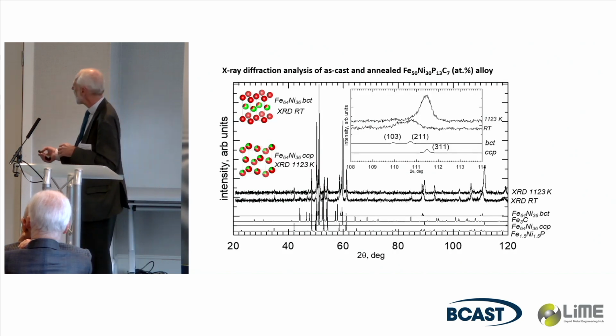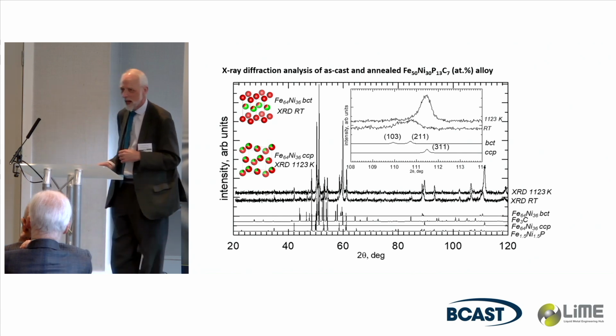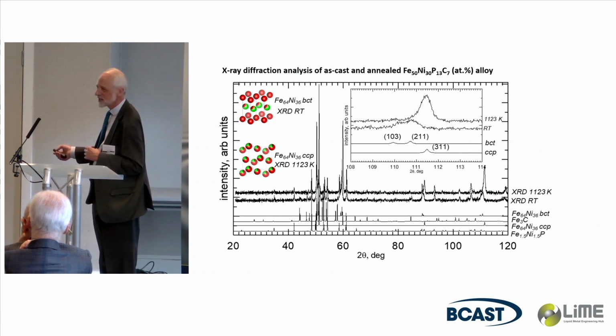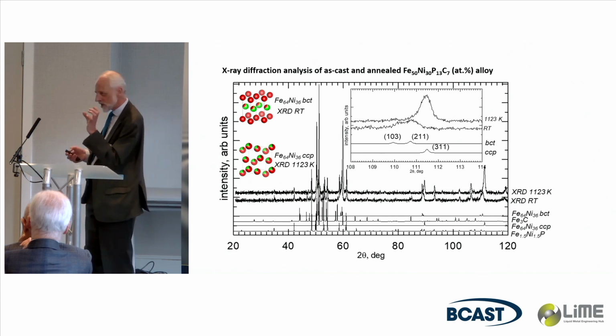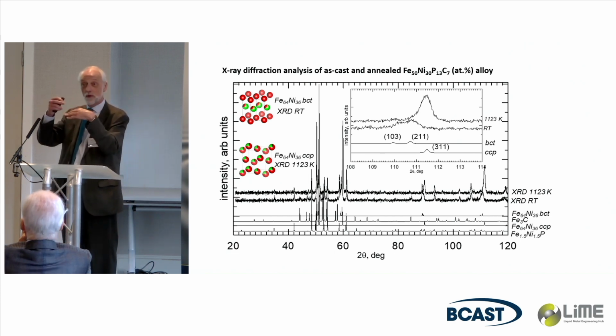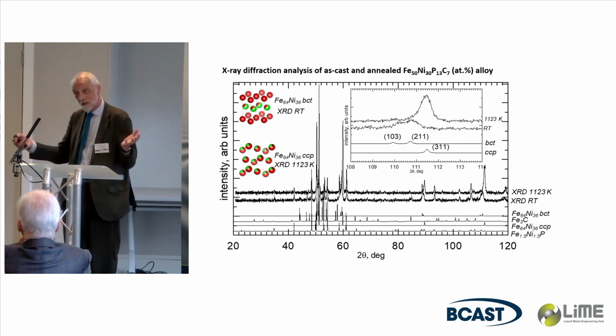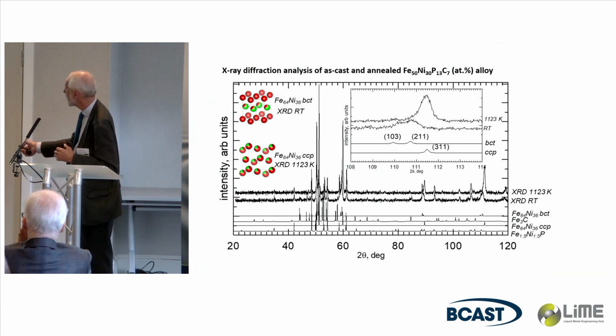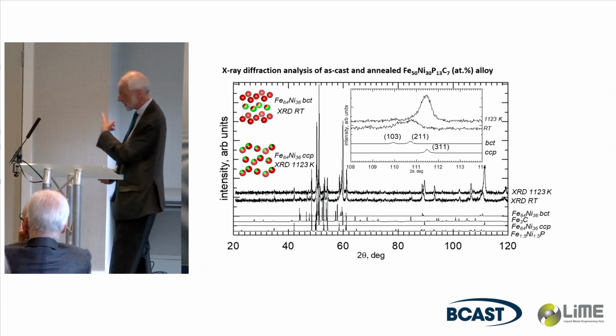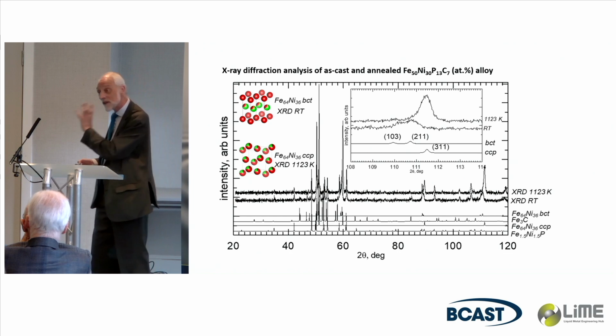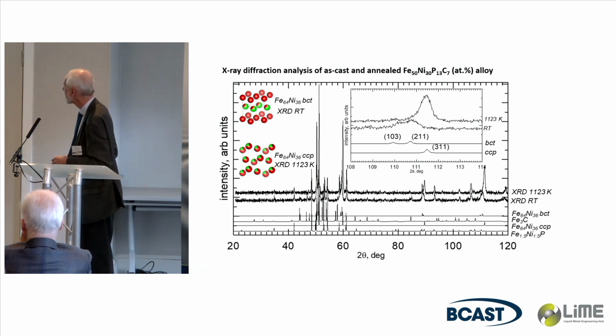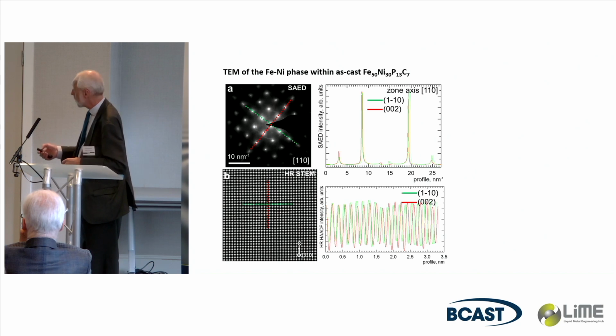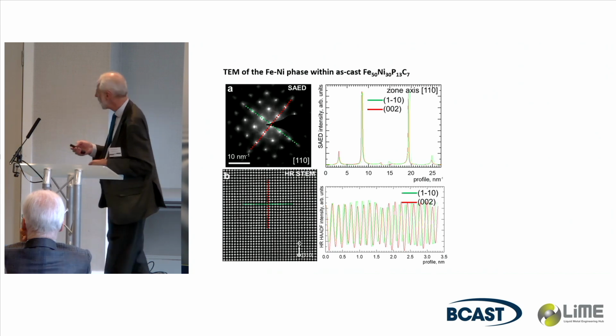And here's a high-angle peak, which is split, which for the face-centered cubic structure should not be split. And it fits exactly what's expected for tetrataenite, where you get the c over a ratio. If you imagine you've got now one unique axis, the c axis, and the a and b are equal, the intensity ratio of the two peaks should be 2 to 1, and the degree of split is the right magnitude. So there was some X-ray evidence for tetrataenite in those dendrites. This, at first sight, would look cubic, but when you measure up closely, you realize it's a bit tetragonal.